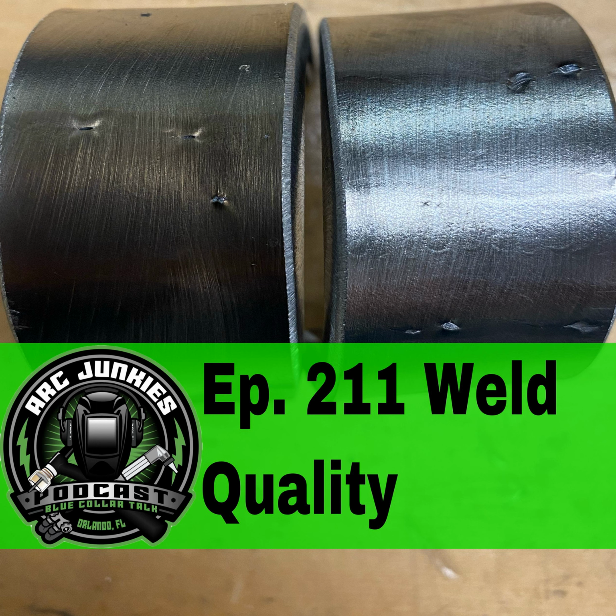So if you don't have an appropriate contact tip to work distance, or what they call an electrode stick out, you're probably going to end up with some uniformly scattered porosity. And the funny thing is, as you're welding, everything looks all fine and dandy, and you're going through the joint, and you get done with it, you lift up your hood, you go to clean everything off, and there's just porosity everywhere. So to eliminate that, keep your electrode stick out where it needs to be, and then make sure you've got good gas shielding.